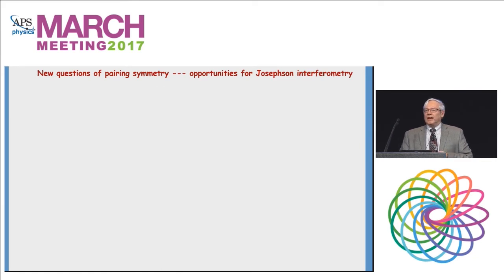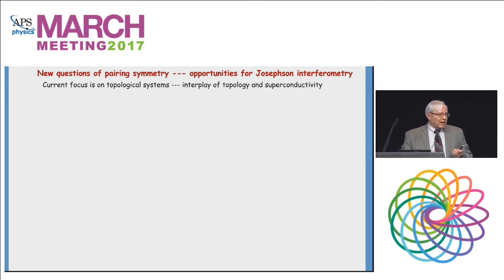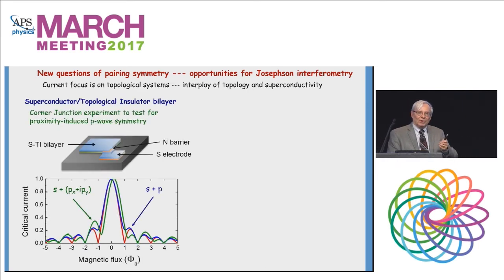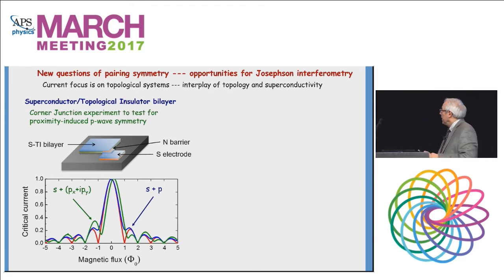Now, there are many other things we're looking at in the pairing symmetry. Our interest right now is on topological systems, as has been pointed out in the previous talks. So a couple of experiments we're working on now, and I don't really have all the answers to, but they show you, I think, things you can do with this technique. We're interested in looking at interfaces between superconductors and topological insulators. There are predictions this would give a p-wave term in the order parameter. That would show up as a deviation from the red Fraunhofer curve as shown here, and it would be symmetric. You might break that polarity symmetry by injecting charge into this. That would pick one of the two spin pairing directions, and that would give rise to something which breaks time reversal symmetry.